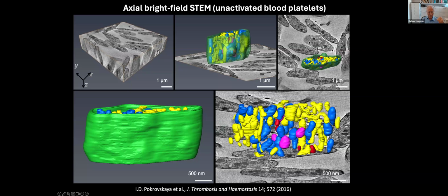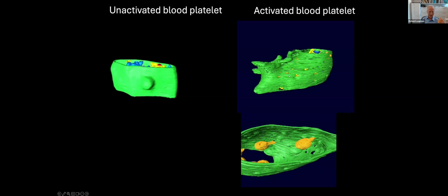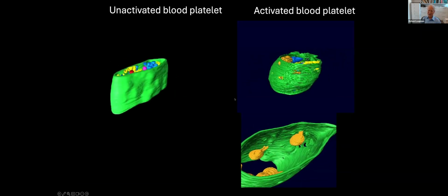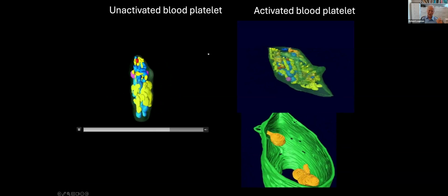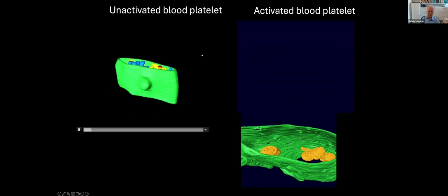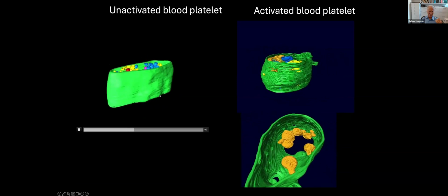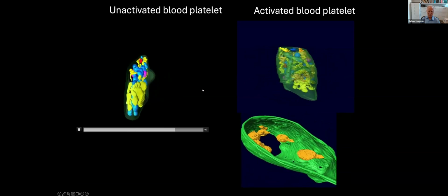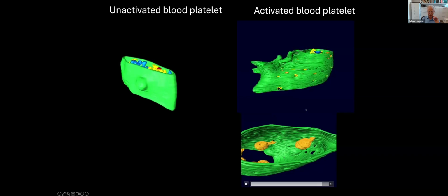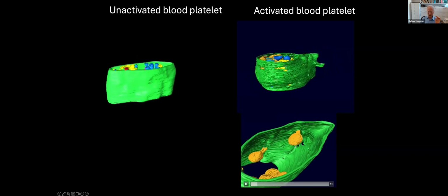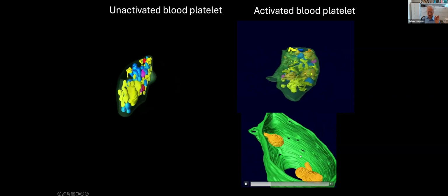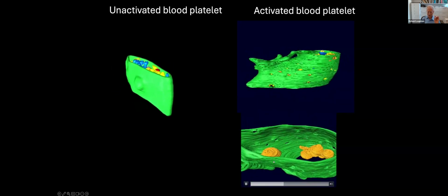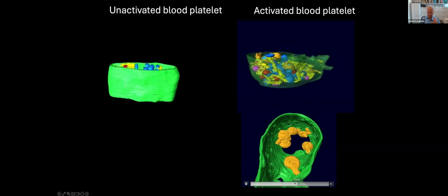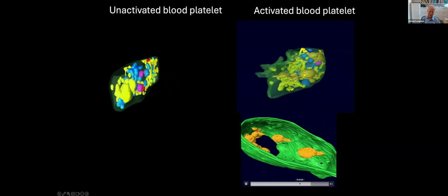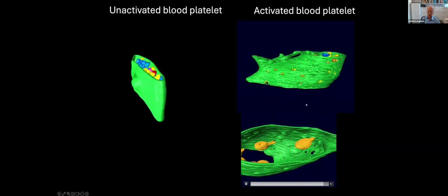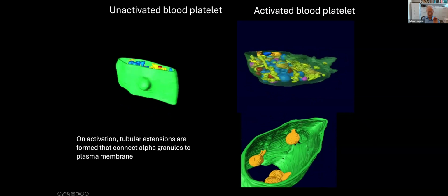And when we looked, and you can see this a little bit clearly here, when you activate these blood platelets, and that activation could be as simple as just drawing the blood, so you have to be really quite careful about making the samples. But when they are resting, you see smooth membranes, and when they're activated, you see these holes appear in the membrane. And those holes, if you look at the inside, are connected to these alpha granules, which are forming necks to the plasma membrane, and they release their contents through those holes. So that was an interesting observation.